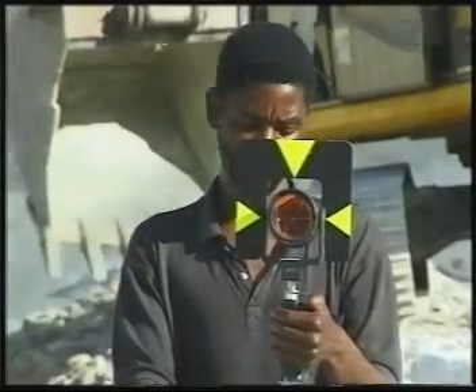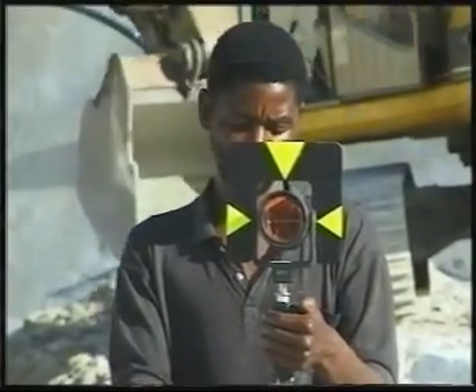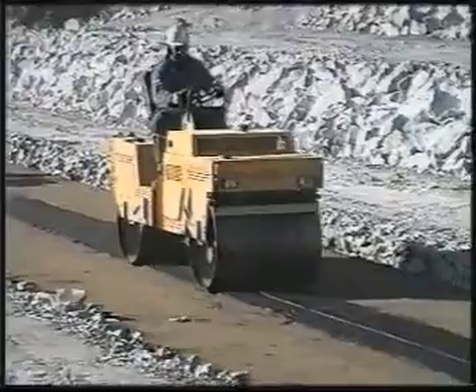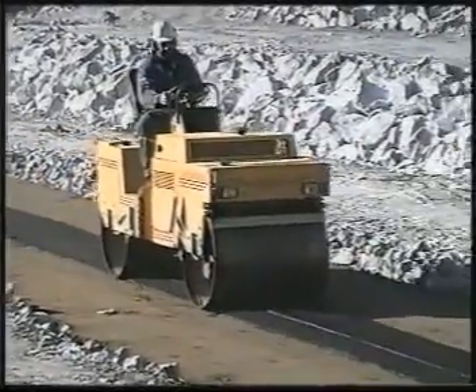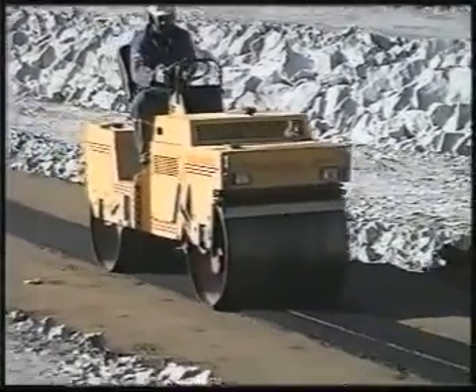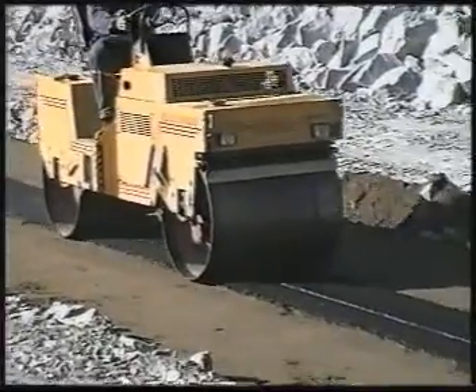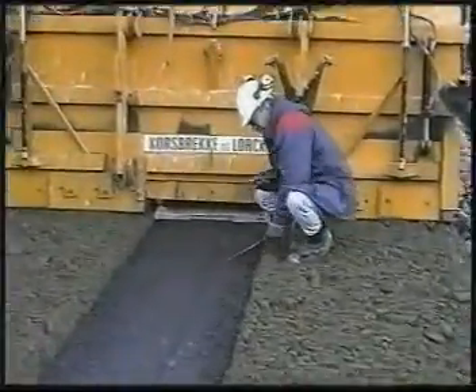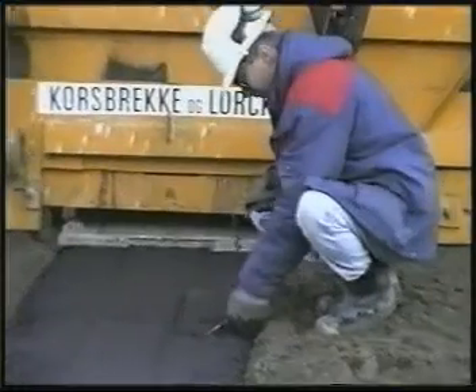The placing of asphalt is systematically controlled. Vital parameters including compaction, permeability, density, amount of bitumen, voids content, etc. are determined and reported daily. Temperature during compaction is of utmost importance.